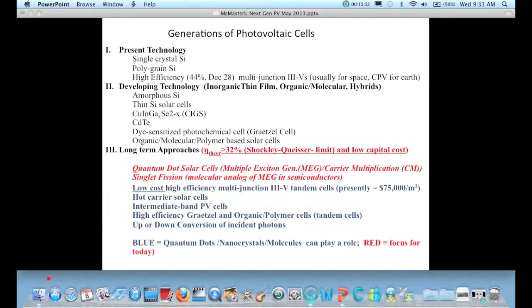In some cases a little bit higher. So they're about 10 to 15% efficient with lower cost, but they don't really change the cost of the energy per kilowatt hour that much, maybe a factor of 2. But to get the real gain, where you need this very high efficiency above the Shockley-Queisser limit with a very low capital cost, that's the goal.